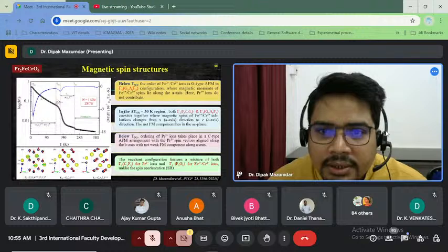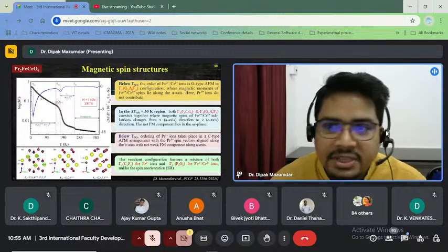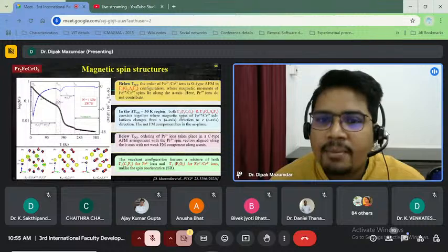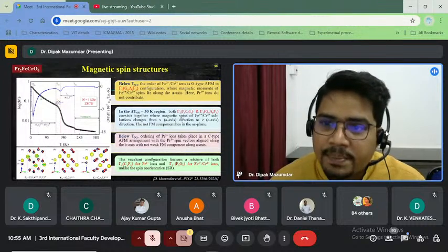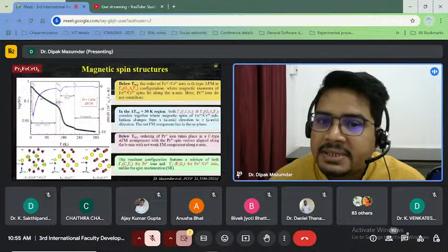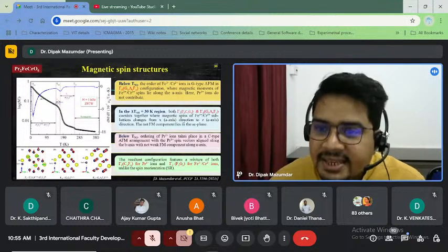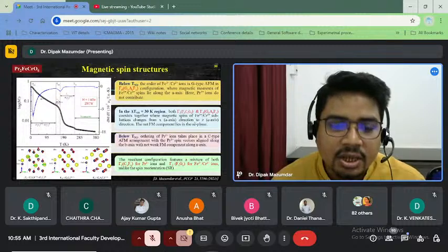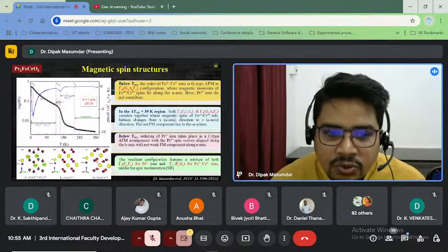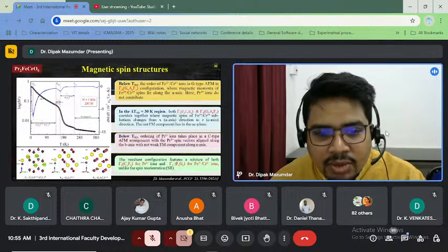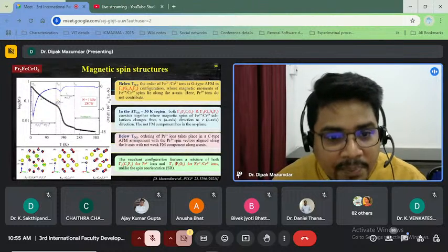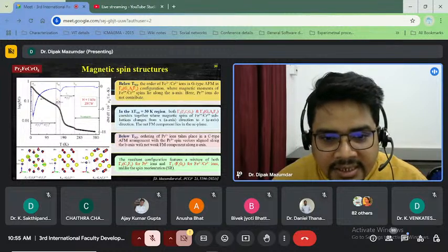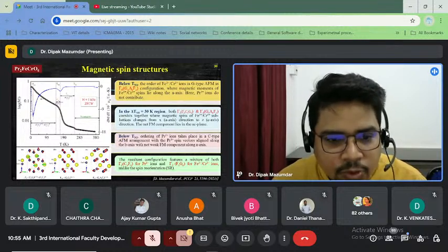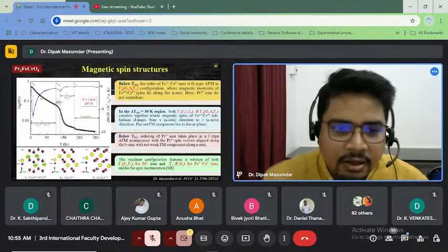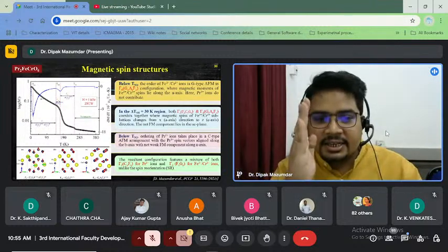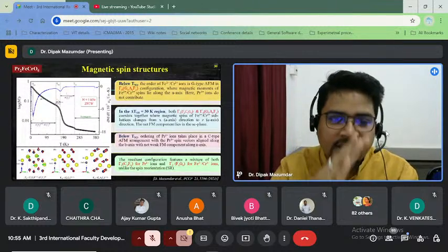In the TSR region, this 30 Kelvin region, both gamma 2 and gamma 4 coexist together, where magnetic spins of iron chromium sublattices change from x direction to z direction. So initially it was along the a-axis, and it is trying to change to the z direction. I am not completely showing that it is from this direction to this direction. I am just showing that it now starts changing. So in the intermediate, I have shown this picture.